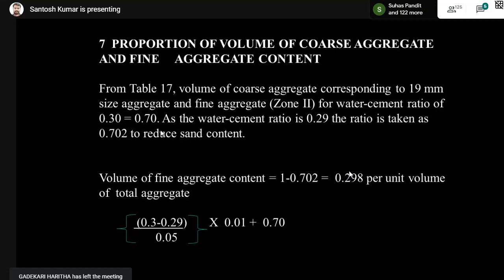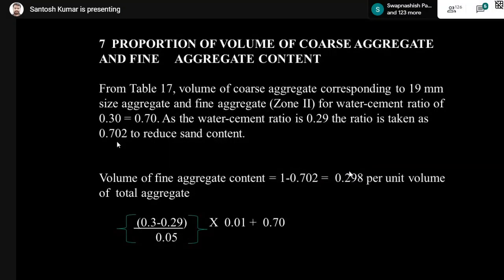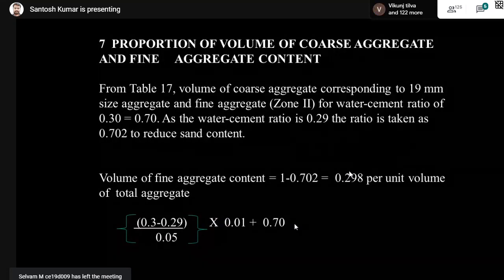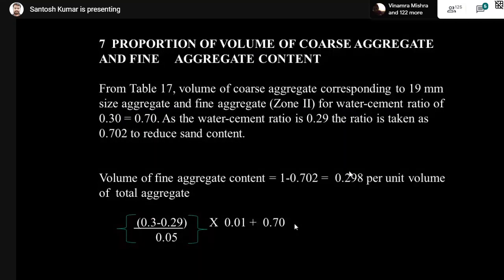As the water cement ratio is 0.29, and the table is for 0.30, the design calculation will vary. So instead of 0.70, we will take 0.702 to reduce sand content. How does this 0.702 come into picture? Just a small calculation. 0.3 is the water cement ratio suggested in the table, but we are using 0.29. So (0.3 minus 0.29) divided by 0.05 into 0.01 plus the volume of coarse aggregate, which is 0.70. If you multiply, it comes 0.702. So that is the volume of coarse aggregate in your concrete. Now the volume of fine aggregate is nothing but 1 minus coarse aggregate volume, which is 0.298.